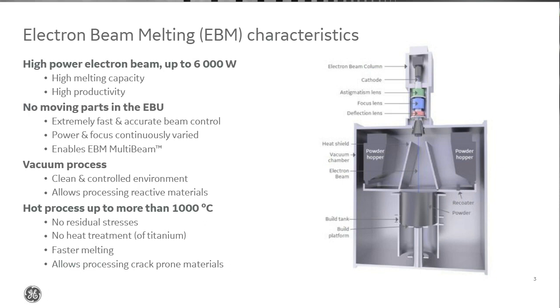And since we are doing all of this within a vacuum, the energy losses are quite small. I typically compare this to running a process within an old thermos, because you are basically within a vacuum, you almost have no energy losses, so the process as such becomes very efficient. And that is why we can keep it at 1,000 degrees and at the same time have a very energy efficient process.